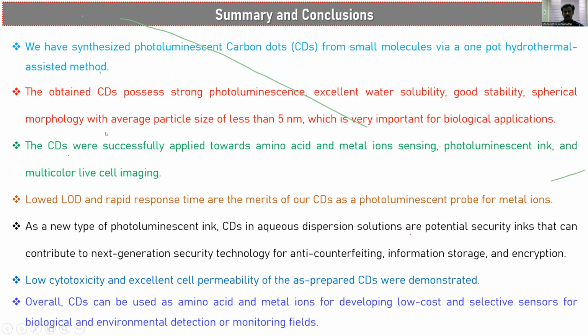Three different materials, we can get less than 5 nanometers, which is very important for biological applications. The carbon dots were successfully applied towards amino acids, other biomolecules, and metal ion sensing. With photoluminescence, we can use them for multicolor live cell imaging. Moreover, the limit of detection and the rapid response time are merits of our carbon dot photoluminescence probe.